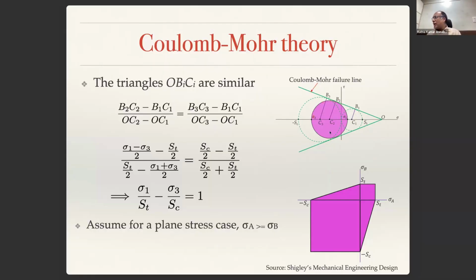So now let us look at the stress state corresponding to sigma 1 and sigma 3. Let us carefully look at this. I am drawing a tangent to this failure surface for the big circle, and that intersects C3, which is for the compression circle, and here B1 C1, which is at an angle 90 degrees from the center. B2 C2, C2 is the center of this pink circle. Now you can see that OB1C1, OB2C2, OB3C3 are similar triangles.